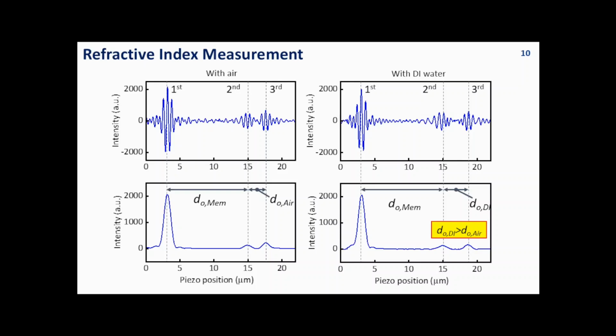When comparing the near-infrared interferometer measurement of air and DI water in the microchannel with the FDTD calculated interferogram, we observe a notable trend of attenuated relative intensity between the peaks. This is because the FDTD calculation assumes optically perfect flat surfaces, whereas the actual surface of the microchannel is not ideally smooth and contains periodic structures smaller than 100 nanometers. This non-negligible surface roughness induces diffraction, which leads to a reduction in peak intensity. Despite the difference in intensity, the optical distance between peaks remains consistent.